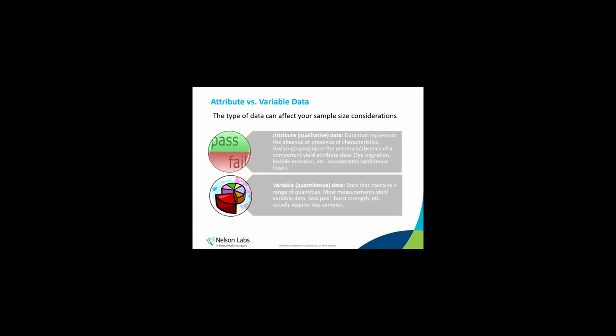I want to touch briefly on attribute and variable data, because this relates directly to packaging validations. Attribute or qualitative data is pass or fail. And so you don't get a numerical value that you can analyze statistically. Tests for package integrity, such as bubble emission or dye migration, are pass-fail tests. Variable or quantitative data is a measured result, and you can run statistics and see how uniform your sample set is. The package strength tests, like peel strength and burst strength, generate quantitative data.